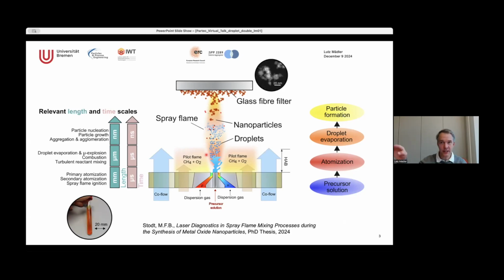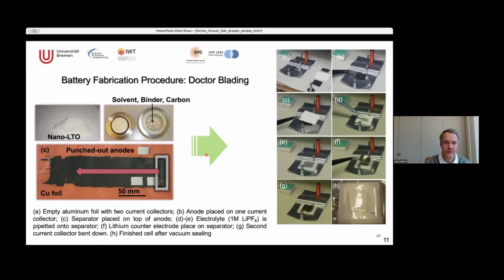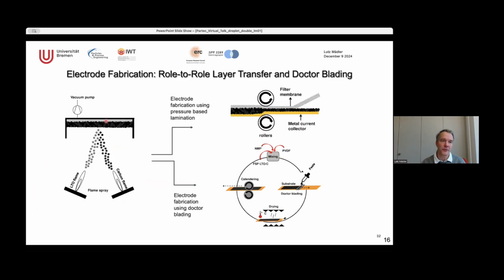Yes, it is. It is actually quite flat. And we have two methods of depositing this. I showed you the lamination process. What you can also do, for the sensors, is put the sensor directly here and deposit directly on the sensor. For this, we use a temperature gradient. The process is called thermophoresis, and the particles are driven towards the cold surface of the sensor, and we deposit directly there. These are super smooth surfaces. However, they are porous. For direct deposition, they're 90% porous, so highly porous, which is super for gas sensors.